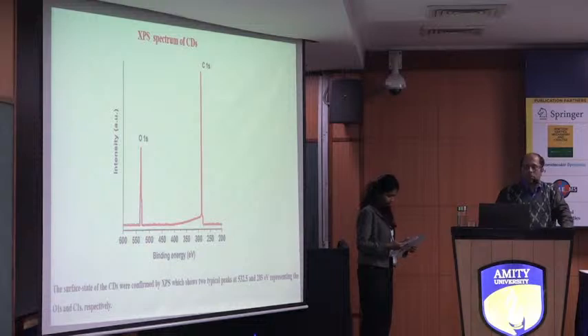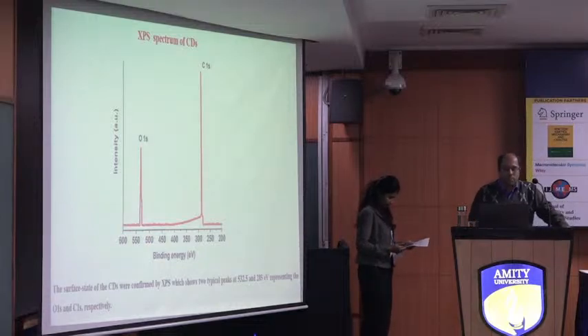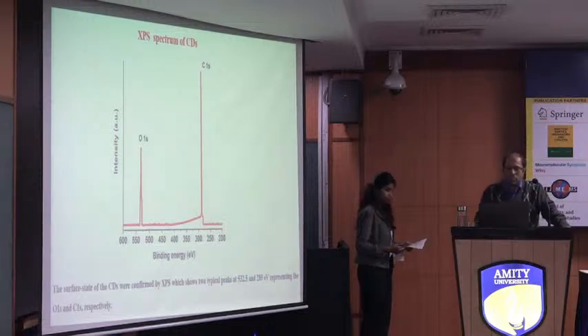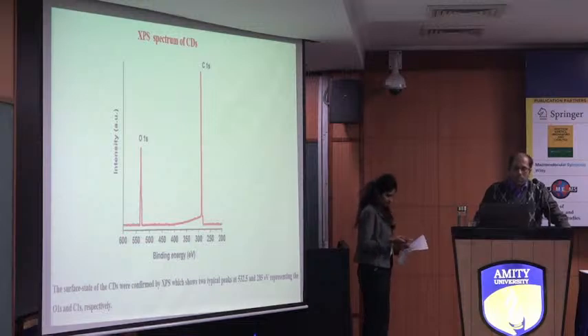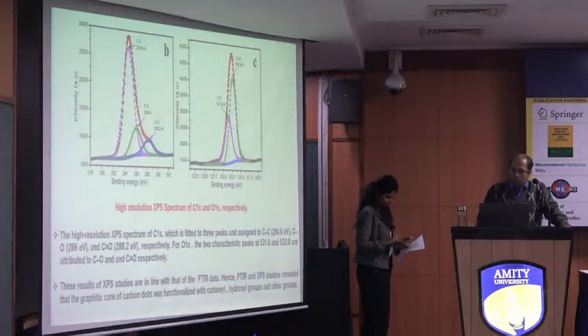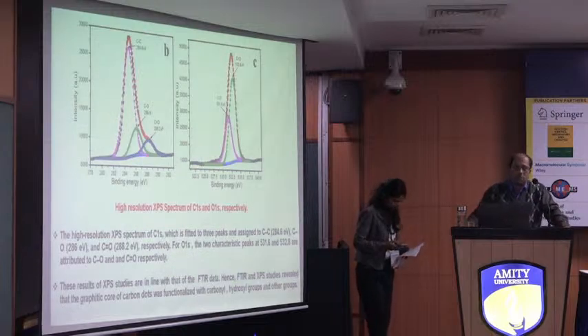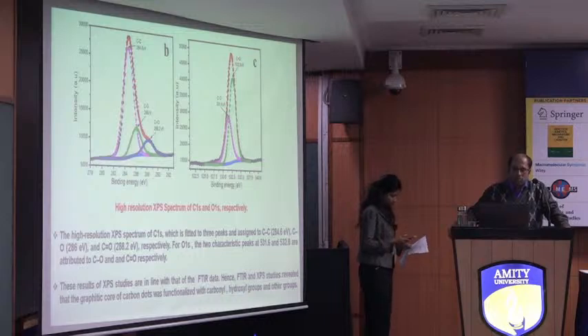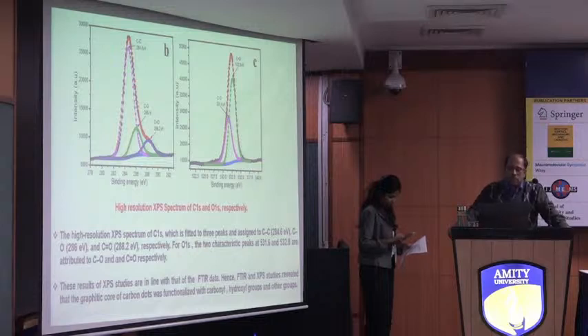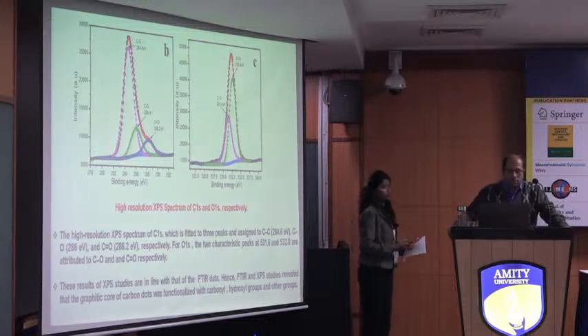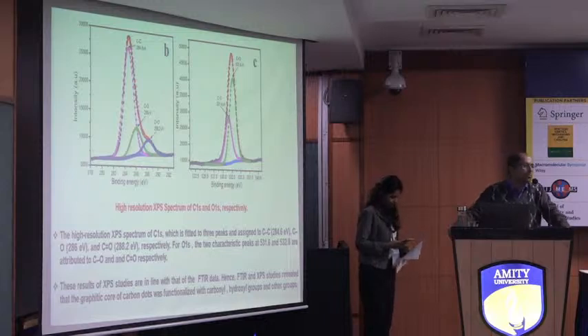Now, in order to confirm more about the functional groups, we also carried out the XPS spectrum of the green synthesized carbon nanodots, which showed two characteristic peaks corresponding to oxygen and carbon, at 532.5 and 285 electron volts. We deconvoluted these peaks and got the high resolution spectra of the C1s and O1s peaks. First, we fitted the C1s peak to 3 peaks, which were assigned to C-C bond, C-O bond, and C=O bond. For the O1s peak, two characteristic peaks were obtained at 531.6 and 532.8 electron volts, which are attributed to C single bond O and C double bond O respectively. These results almost exactly match with the results obtained from the FTIR studies.